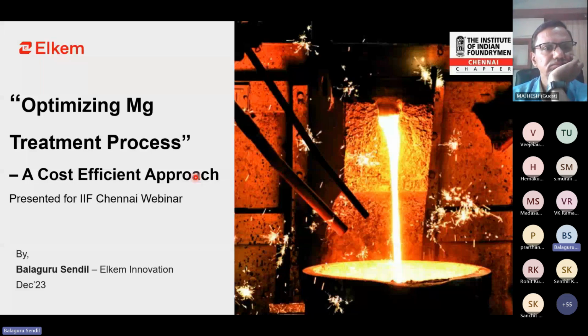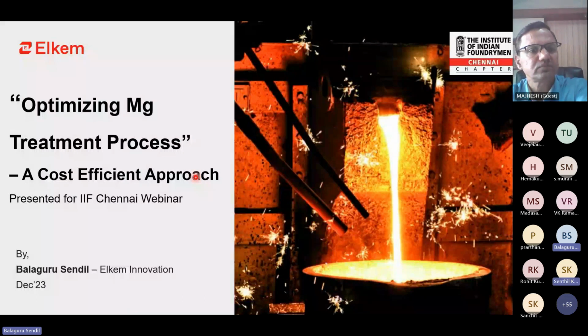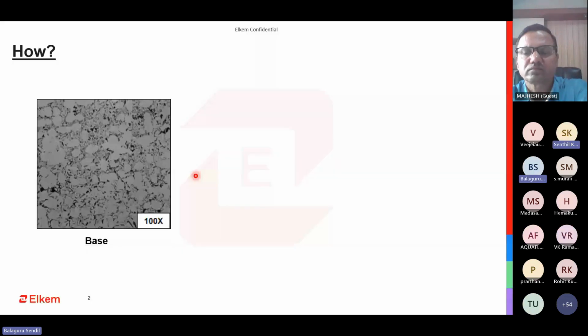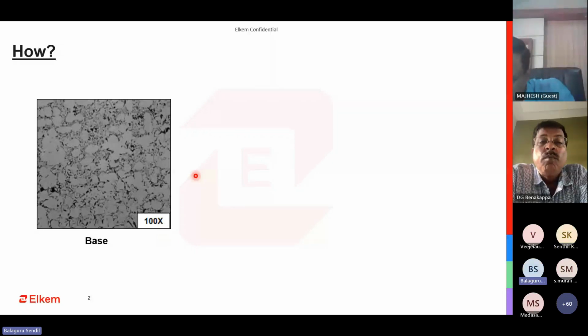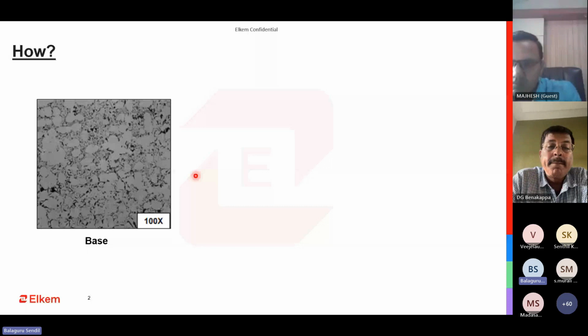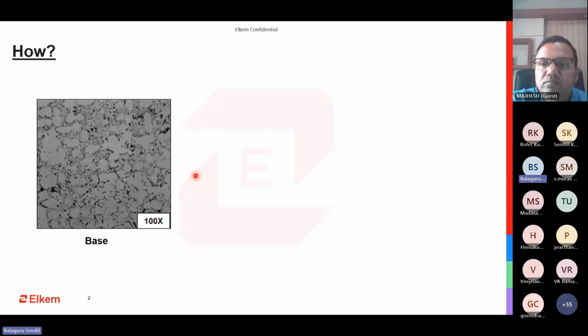Pushing to the next slide, we have seen a microstructure like this. People who are making ductile iron, who are continuously checking its quality, since most foundries do it, if you take a base metal, pour a micro sample and look, you will see something like this. This is the base metal, how it looks. We have some amount of carbon in our system, and then we have iron and silicon. There is only a certain amount of carbon that can go into your iron and silicon system. The rest of the carbon that you are voluntarily adding to your iron and silicon system will be thrown out. If you look at the typical iron carbon diagram, something more than 2% carbon is the maximum solubility for a particular silicon level and iron level. The rest will come out.